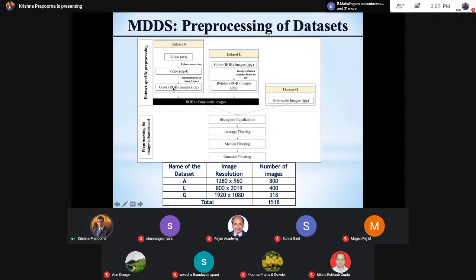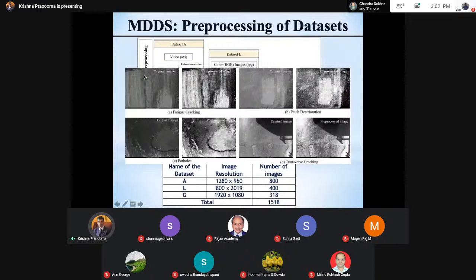We did that pre-processing, and then we enhanced the image with equalization and filtering. We use Gaussian filtering techniques that gave us better confidence. Yeah, this is what we should be doing, and this is what we found. So the original image you see here, this is the pre-processed image.